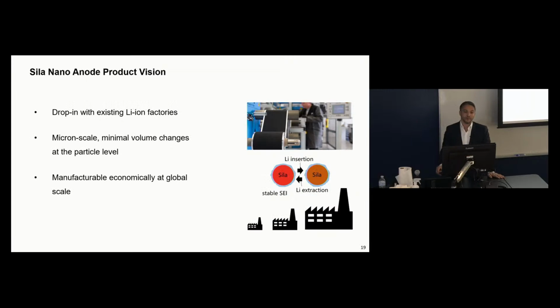So when we started the company, we envisioned that we wanted to develop a certain type of product. We wanted to make sure that our product will be compatible with lithium-ion battery factories, present, past, and the future. And so conventional materials, they're typically micron scale. So we wanted to develop micron scale particles that would also exhibit very small volume changes at the particle level in order to get this stable SEI. And we also wanted to make sure that whatever we develop is going to be manufacturable economically at a global scale. What it means is that when you build large reactors, the large reactors should be inexpensive to build. It means that if you use some materials or precursors, they have to be inexpensive and available on massive scale. So it put significant restrictions on us, but it was worth it.